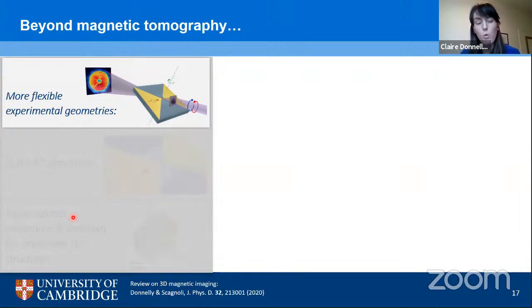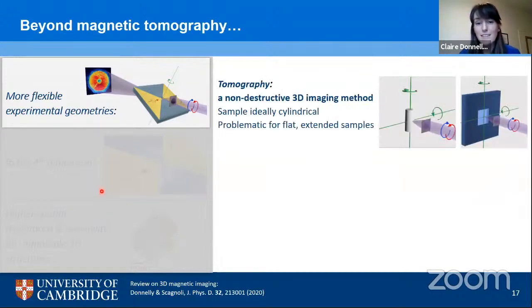So your question may be, why is this necessary? Why is tomography not a one-size-fits-all technique? And the answer is quite simple, actually. Tomography, I must emphasize, is a technique where the rotation axis is perpendicular to the X-rays, or to your probe. Now, this is particularly advantageous for cylindrical samples, such as the pillar that we saw in our first measurement. However, when we go to flat extended samples, such as a silicon nitride membrane that we often use in X-ray measurements, when we rotate our sample up at a certain angle, we will actually block the X-ray beam. We'll lose angular information and we can introduce artifacts into our reconstruction.